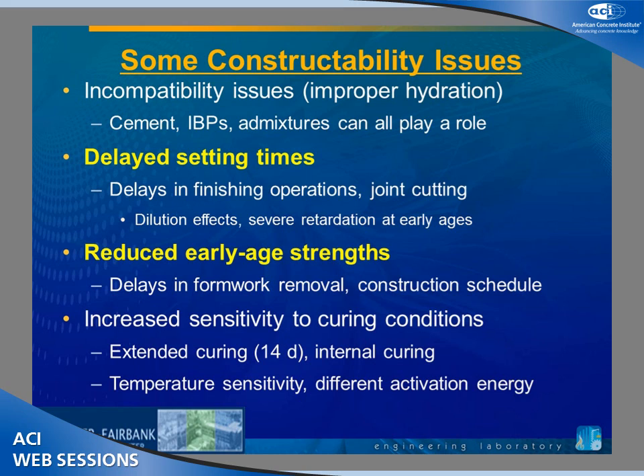Kind of something that goes along with this is the reduced early age strengths. You got to realize that if you're taking 40 or 50 or 60% of your cement out of your concrete, the cement is generally the most reactive material. And so when you put in that much less cement, you can expect less reaction, less strength at early ages under normal conditions unless you do something to try to account for that.